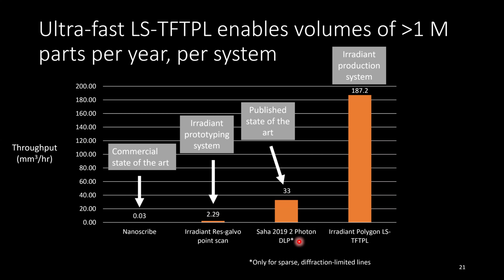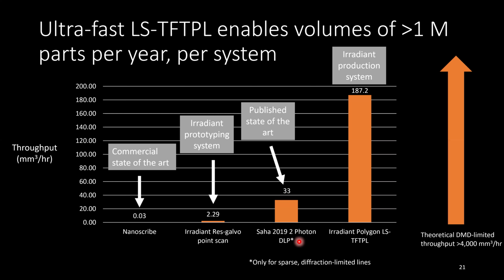So whereas with a point scan system you could make maybe 400 of these components per year, 10,000 times faster, you now start talking about 4 million components per year per system. And then this is actually still very far from the full theoretical DMD limited throughput of these sorts of things. So we think there's several orders of magnitude improvement here. And we actually have a pretty large 2-year DARPA program right now, where one of the main focuses is on taking this speed that we've demonstrated already and increasing that by another factor of 3.